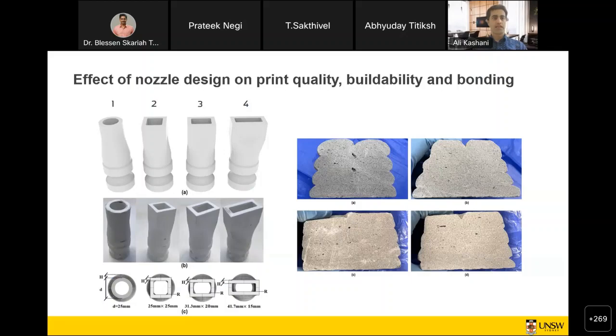So we looked at the circular nozzle, the square nozzle, and rectangular nozzles with different aspect ratios, as you can see in this photo. And these are the results of each of those nozzles. We printed 2 layers side by side, and as you can see, the layer height and the width are different based on the nozzles that we use. And there might be some gaps developing between them when we print 2 layers next to each other.